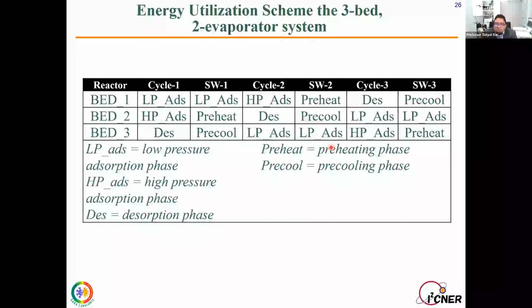So how this works, it has a little bit more. Instead of 4 modes, it has 6 modes. Bed one initially worked in the low pressure adsorber mode. Then the switching period is also low pressure. Then it goes to high pressure mode, then preheating, then desorption, and also pre-cooling. Here we have some optimization, as you can see.